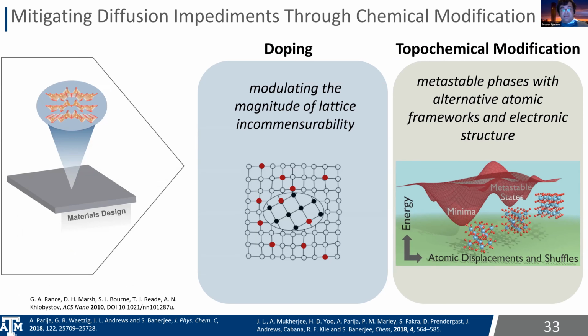Okay, so you can modify structures to reduce the elastic misfit strain by changing the degree of lattice incommensurability. So really the idea here is that we've got two phases, right? Two differently lithiated domains. And by incorporating dopants, could you bring them closer to each other? So that's one idea we've been pursuing. And a second one is, could you altogether go towards entirely different V2O5 frameworks that don't have some of these design flaws that this orthorhombic phase of V2O5 had? And of course, the major design flaw is the square pyramidal nature and its split off conduction band that gives rise to these polarons.